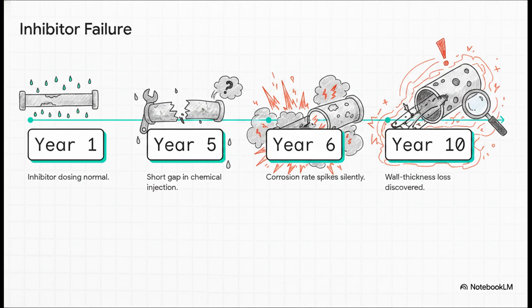Imagine it's year 1. Inhibitor dosing is completely normal. But in year 5, there's a short gap in chemical injection due to maintenance or maybe some supply issues. Because the water cut is higher by year 5, that short gap allows an invisible, aggressive corrosion spike. By year 6, the damage is already done, but you won't actually know it until year 10, when you finally run an intelligent inspection tool through the line and discover that your critical wall thickness is completely gone.